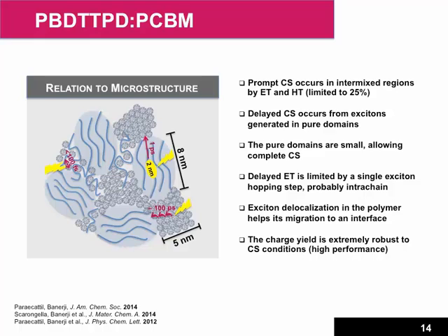And then we said that the more delayed electron and hole transfer processes occur from the pure regions of polymer and fullerene, where the exciton needs to diffuse to a charge separation site. But still, from this annihilation study, we could tell that the polymer domains are about 8 nanometers large, and it's still very fast to consider that an exciton can diffuse over 4 nanometers in 1 picosecond.